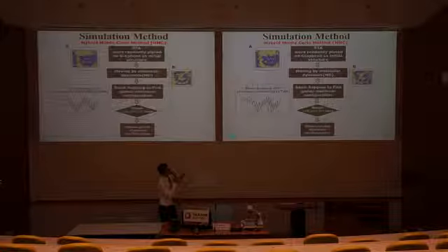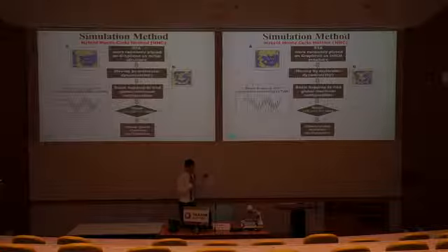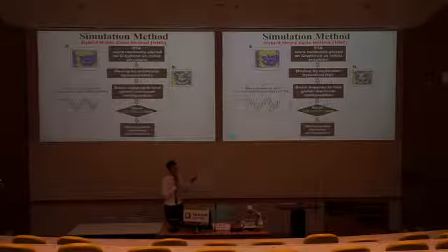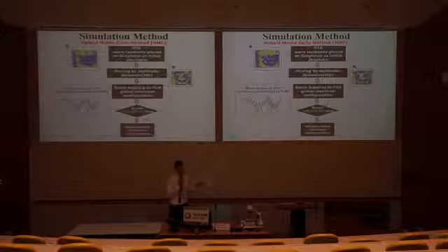This is our HMC method flowchart. First, the STA molecules are randomly placed on the graphene as the initial structures. We use MD to make the STA molecules move around. After that, we use basin hopping to find the global minimum configuration, and we save the stable structure each time. We repeat this process 100,000 times. Finally, we obtain the global minimum configurations from this procedure.